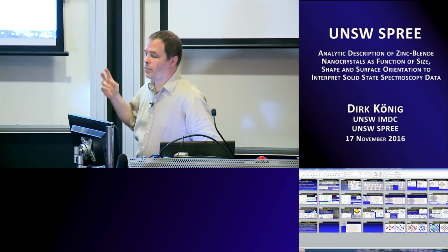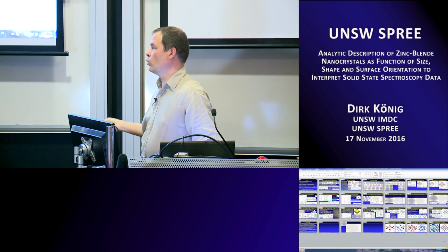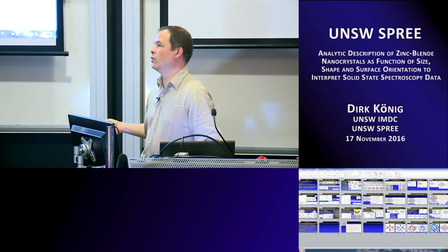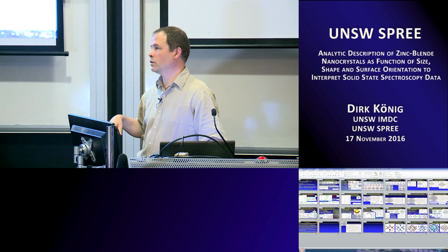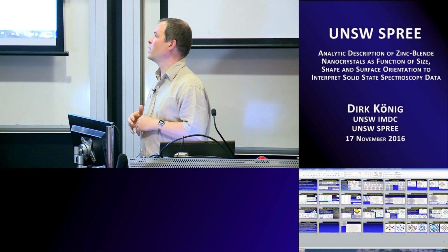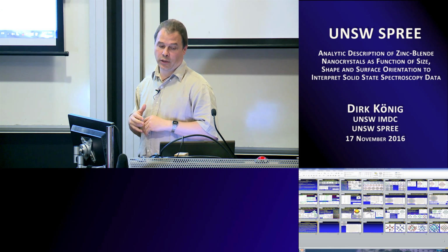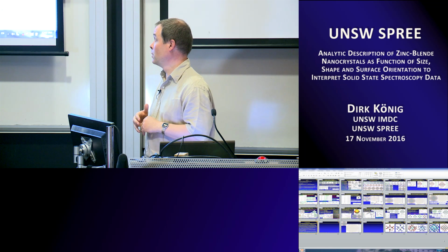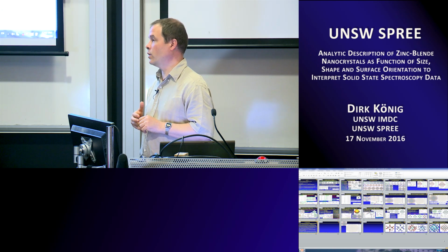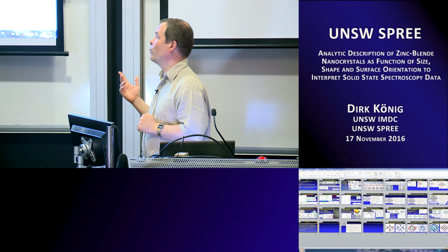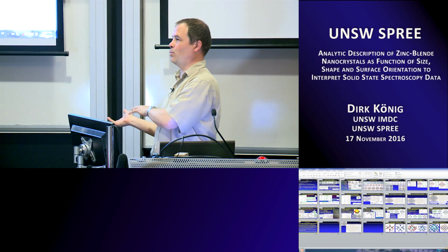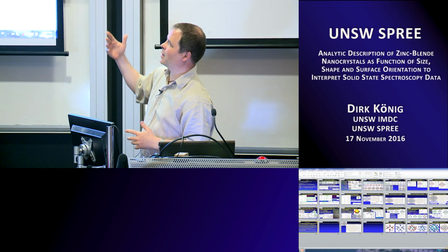There are actually two answers. It depends on how much excess silicon you put in the samples and on your processing, because I know groups which have fairly regular crystals. But depending on what you want to do with the crystals, you may put in so much silicon that you get an interconnected network, because that's more conductive. Then you obviously get crystals of elongated shape, and that goes into a nanowire description. I don't have the time at the moment, but next year looks a lot different, and I can work on these nanowire descriptions because that's also very interesting for the ULSI industry. What we can do there is quite nice, because we treat the crystalline structure in only two dimensions, so we get a degree of freedom and can play with faceting or ratios, which you really can't with these crystals.